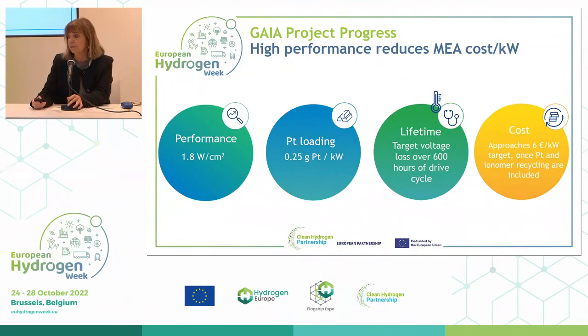So in terms of the overall project progress, performance, 1.8 watts per square centimetre was obtained with a platinum loading of 0.25 grams of platinum per kilowatt. And so this high performance clearly reduces the MEA cost per kilowatt, because we haven't increased the platinum loading there. The lifetime, we achieved the target voltage loss over the first 600 hours of operation in that automotive drive cycle. And the cost, once we take into consideration the possibility of recycling of the ionomer and the platinum, then it actually approaches the target of €6 per kilowatt without actually reaching it. And so overall success, this high performance, I think that's the take-home message. It reduces the cost per kilowatt.